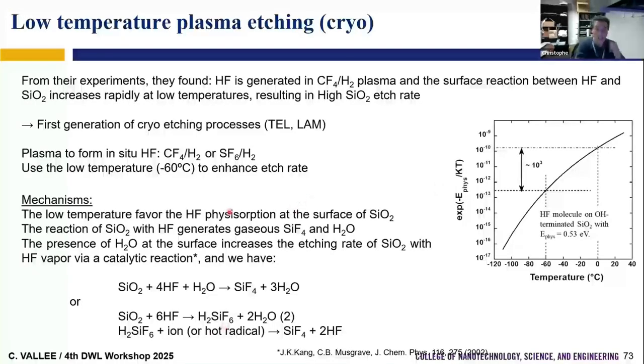And in addition, they observed that they had some water. And in fact, it is said that the water is adding to the etching, because we know that when we do HF vapor or HF etching of silicon oxide, if we add water, we have a catalytic effect. This water promotes the etching of SiO2 with HF, promotes the bonding of fluorine to silicon. And then by the presence of water coming from the first etching reaction, where we form water, we enhance the etching rate. And with the ions, you add the ions to enhance this reaction.